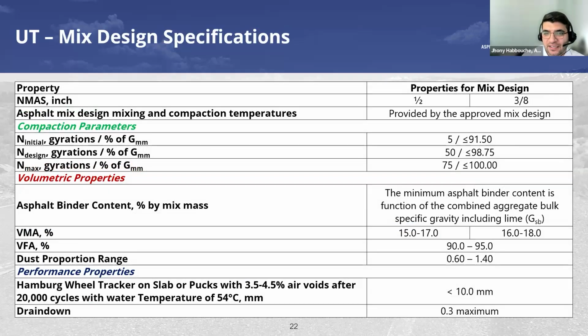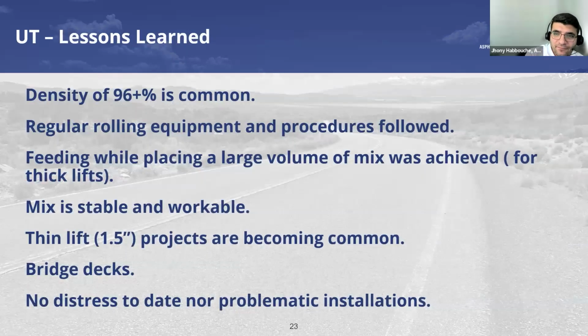Their requirements on the volumetric properties are different when we start talking about VMA, VFA, even the percent binder content, and then they do add a performance requirement, especially at high temperature. I want to mention that the requirement on the Hamburg wheel tracking test, the HWTT, has recently been modified. This hasn't been updated in the slide yet, but I believe the 10 millimeter went down to 7, if I'm not mistaken. I need to go and pull the specification again.